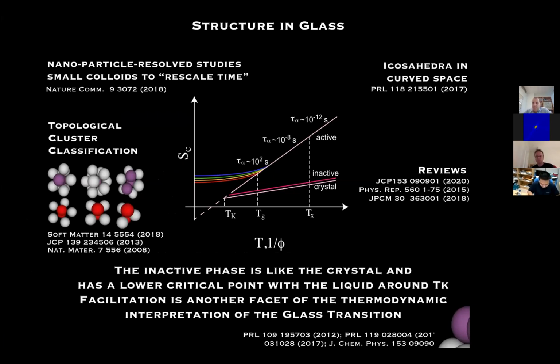I have a few questions. First of all, you mentioned that this icosahedra or some kind of local structure is important in the dynamics of the glass transition. Somehow, my understanding is that when you bias this mu ensemble, you somehow have a dynamic coexistence of one phase moving faster, another phase moving slower, right? So my question would be, this icosahedra, in my opinion, the hard sphere is very special. The hard sphere is very special in such a way you have this kind of icosahedral cluster. It packs better than FCC when your cluster is small enough.